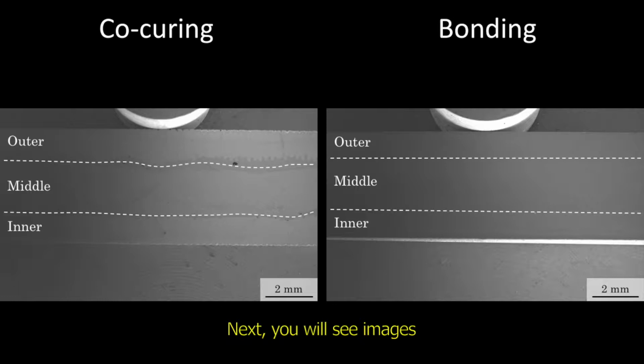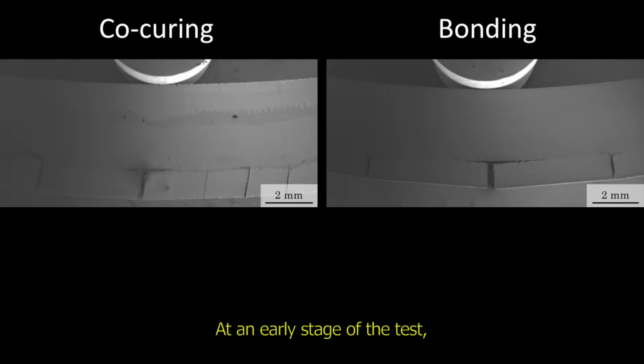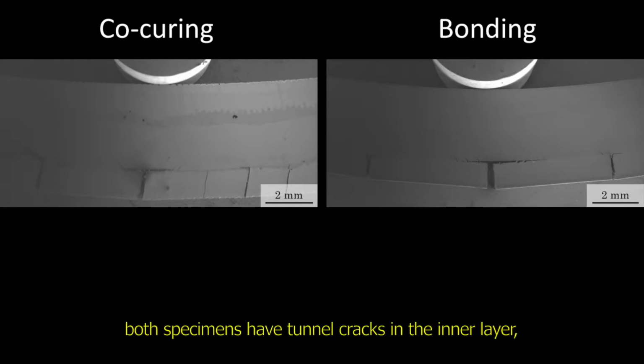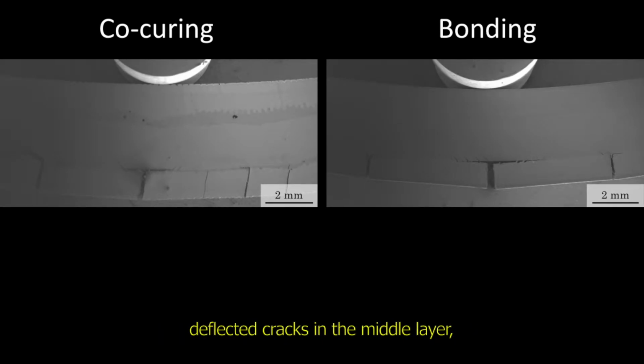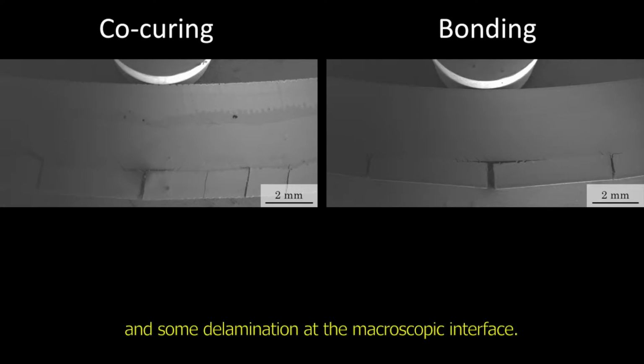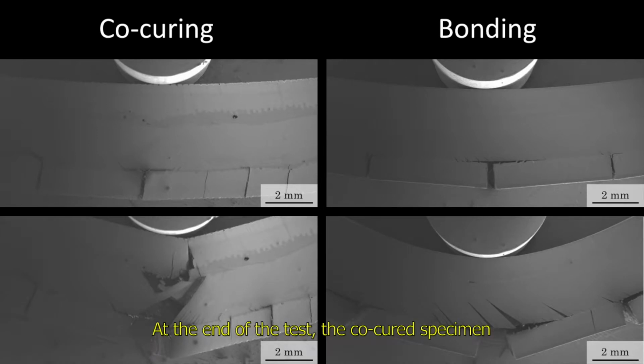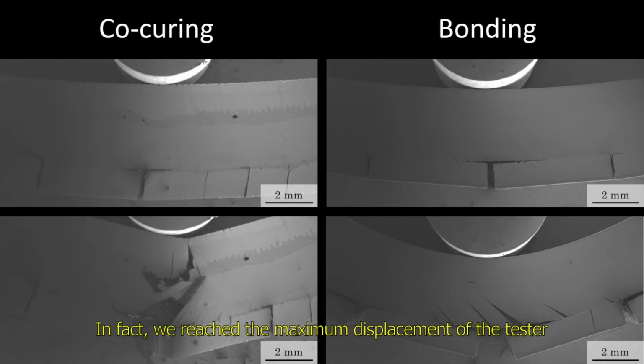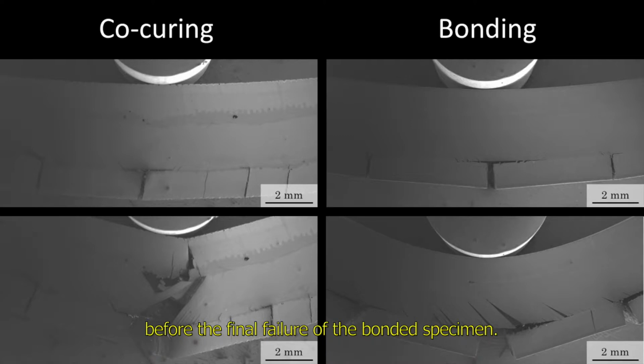Next, you will see images at an early stage of the test and at the end of the test. At an early stage of the test, both specimens have tunnel cracks in the inner layer, deflected cracks in the middle layer, and some delamination at the macroscopic interface. At the end of the test, the co-cured specimen has failed completely, while the bonded specimen is still carrying load. In fact, we reached the maximum displacement of the tester before the final failure of the bonded specimen.